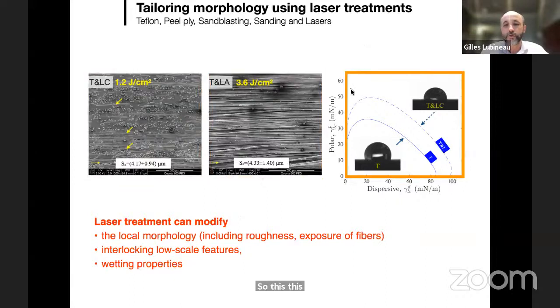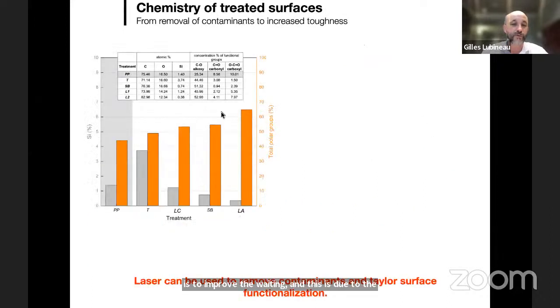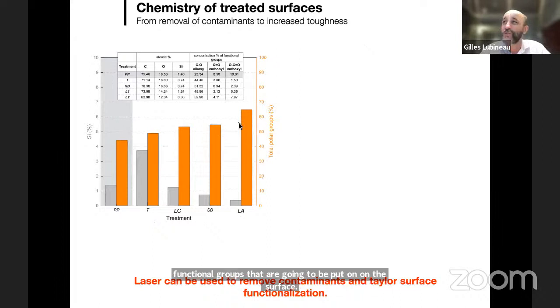This surface treatment influences a lot the surface properties of the composite, because if you look at the wetting, for example the polar and dispersive component of a wetting test, here you have the wetting envelope that you have on a pure Teflon surface, I mean on a CFRP treated with a Teflon film, and here the wetting surface after laser treatment. So you see that the first effect of the laser treatment is to improve the wetting, and this is due to the introduction of polar groups on the surface. If you look at the number of polar groups, that means functional groups that are polar, on the surface, these are increasing with the laser treatment. So this is the first effect.